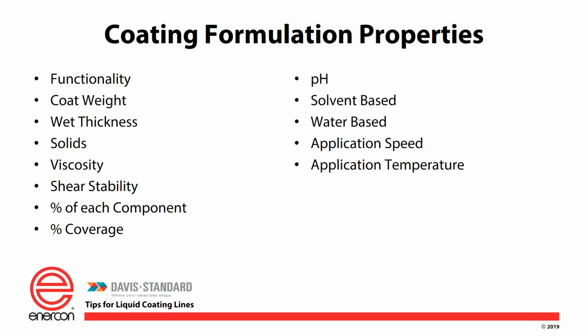Now, shear stability. Each coater actually creates a little bit of shear when you're applying the coatings. If your coating is not a stable coating and breaks down, then we want to use a very low shear application method. Whereas if it takes a shear to apply it, then we might add more rolls. Like on silicone coating, 100% solid silicone coating can be done with a 3-roll offset gravure coater, which is typical for the US markets, or a multiple roll, such as a 5-roll smooth transfer roll coater, which is typical for European markets. Each roll is nipped together.